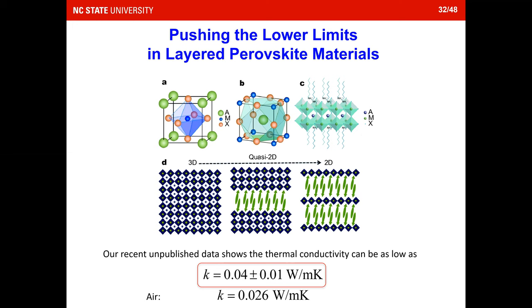And just a short time ago, my student told me that, well, the measured thermal conductivity is very promising. We showed that the thermal conductivity of these layered perovskite materials is actually even lower than the record of 0.05 in a fully dense solid. So what we achieved is 0.04 plus or minus 0.01 experimental uncertainties. So this is even one step further to suppress thermal conductivity in a fully dense solid. And as you can see, this is much closer to the air than the 0.05.